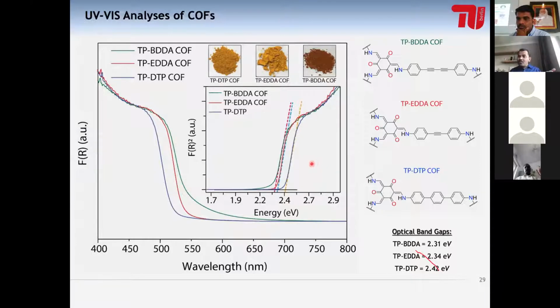And what we observed was the other 2 materials, for example, TP-EDDA having the acetylene moieties, and the TP-DTP having phenyl moieties, absorb more in the UV light region, which was expected because their band gaps were pretty higher as compared to the TP-BDDA having the diacetylene moiety. So now it was the testing time for us.